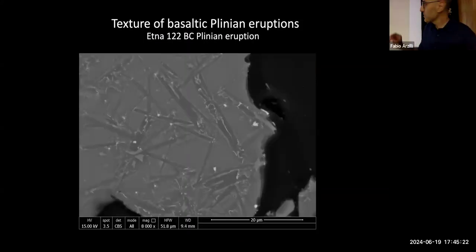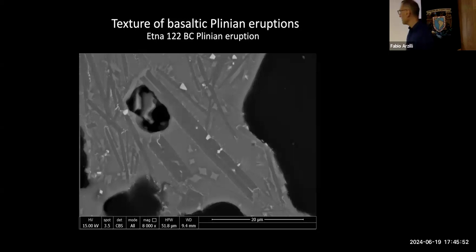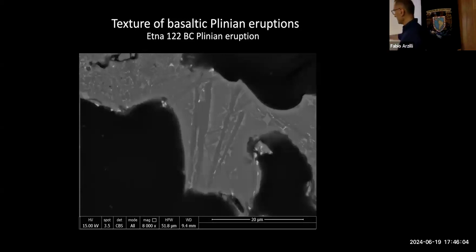So if we observe the textures in basaltic Plinian eruption products, we observe that they are very rich in microlites. This is the glass, these are plagioclase, and then we observe tiny pyroxene that can nucleate heterogeneously on plagioclase, with these plagioclase that have these skeletal shapes. I can show you another example here. So this is the plagioclase, this is the pyroxene. This is the heterogeneous nucleation of pyroxene on plagioclase, with these swallow-tailed shapes that are related to high undercooling. So these shapes are usually related to high undercooling.